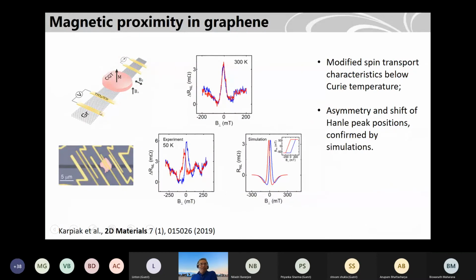So for example, we transport spins from graphene, and they go through this heterostructure and we detect on the other side. So this is the Hanle experiment at room temperature. These are the blue and the red curves. You see when you sweep up and sweep down, there is not much change. But when you cool down the system below 50 Kelvin, which is below the Curie temperature of the 2D magnet, we see a splitting of the curves, and we could explain that due to the magnetic proximity effect.